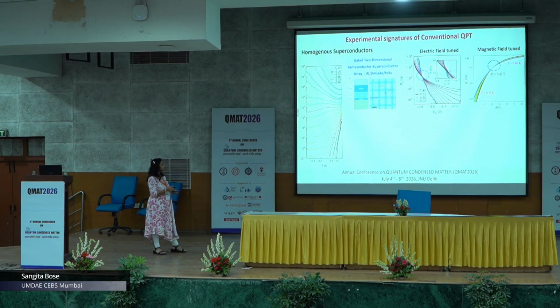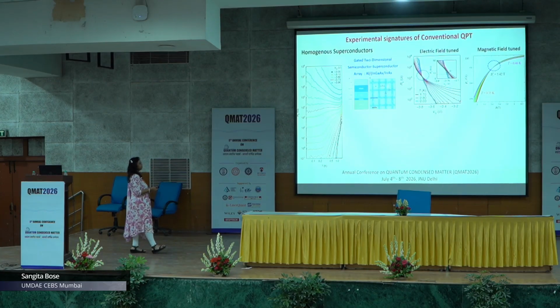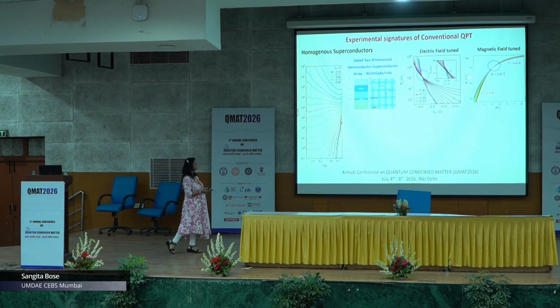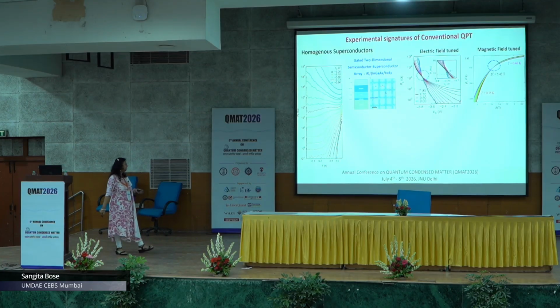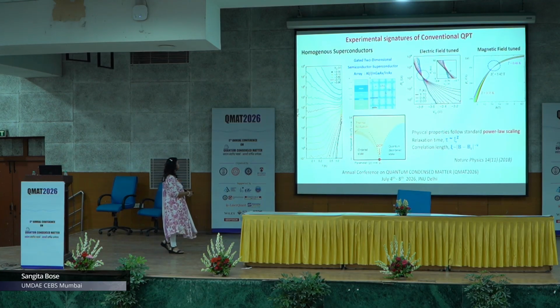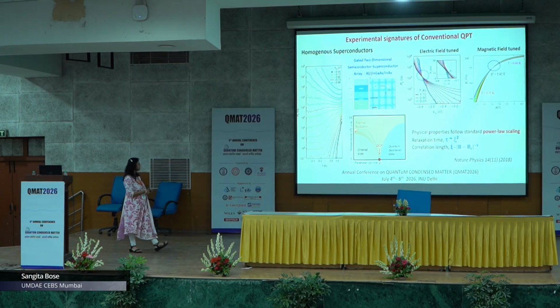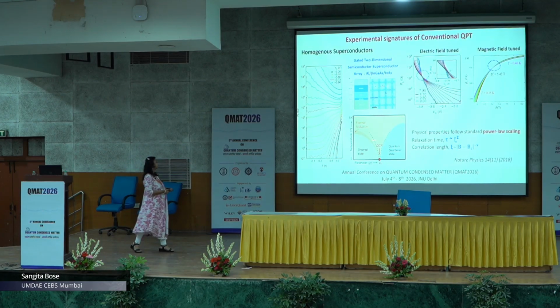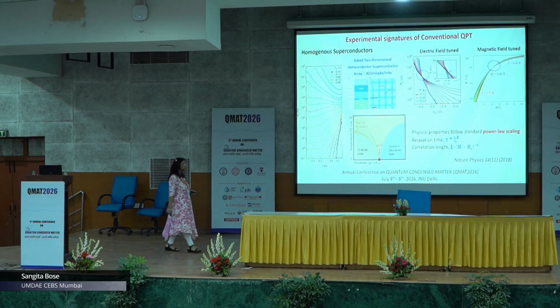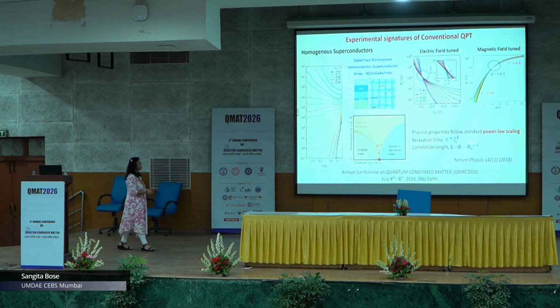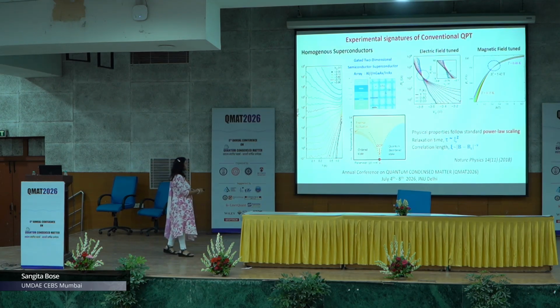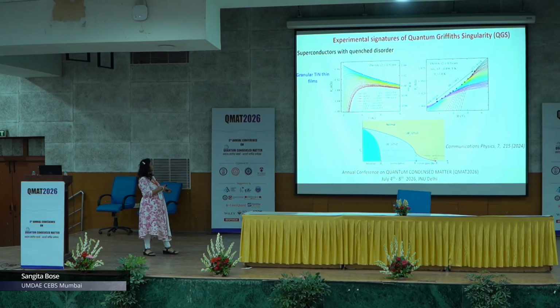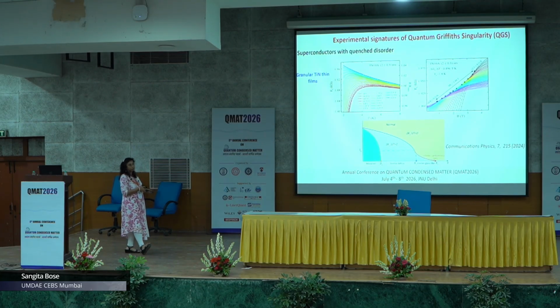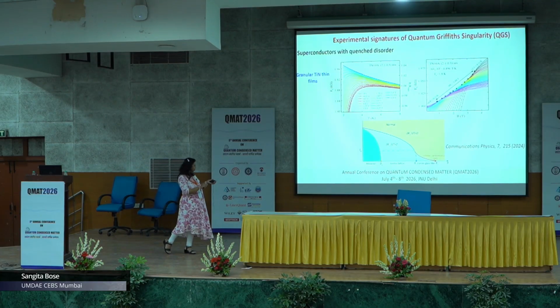This is the classic experimental signature of a quantum phase transition in these systems. This was electric field tuned, and since I will be showing a lot about magnetic field tuned systems, this is a similar result where you see these magnetoresistance isotherms with a single crossing point, that is, a single quantum critical point in these SIT-driven systems. How does the phase diagram look? You see this ordered to disordered phase transition driven by this parameter PC, and you have this quantum critical point. In the quantum critical regime, the physical properties follow standard power law scaling, where the relaxation time diverges with a power law behavior. Now, if you go to different kinds of systems where superconductors have quenched disorder, previously those were systems that were more or less homogeneous.